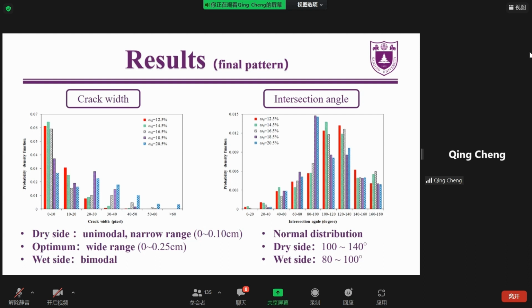with a dispersed structure, we can find that most of the intersection angles are in the range of 80 degrees to 100 degrees. And the peak value of the probability density function is at around 90 degrees. This corresponds to the observation that for the soil samples with a dispersed structure, the subcracks initiate after the formation of the primary cracks. The subcracks have intersections with an angle of about 90 degrees.